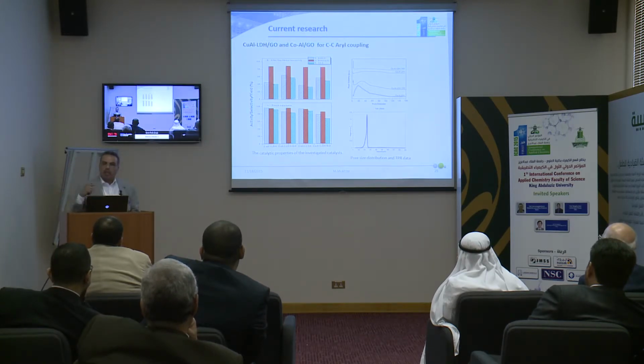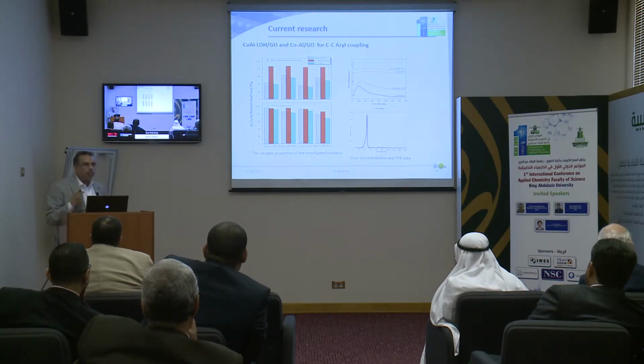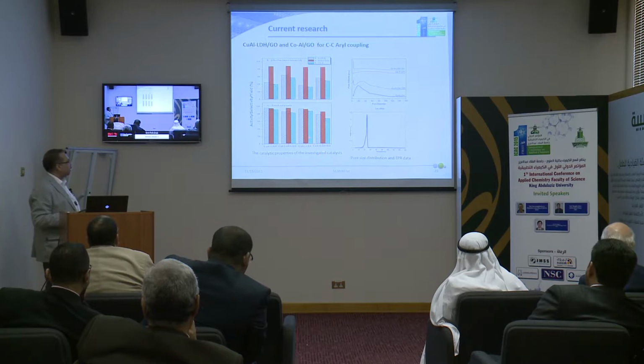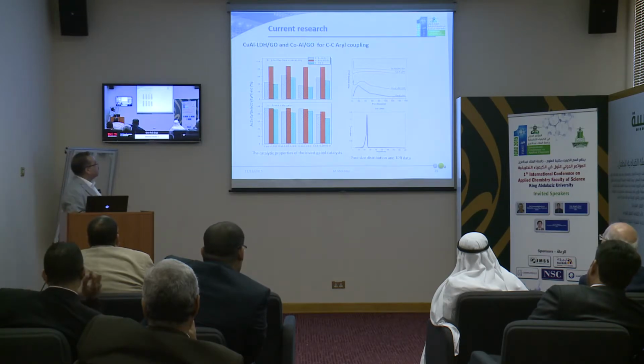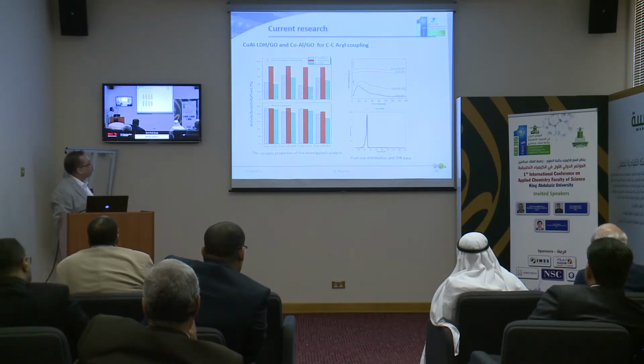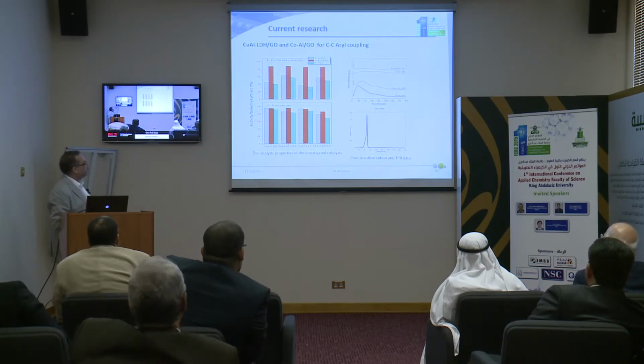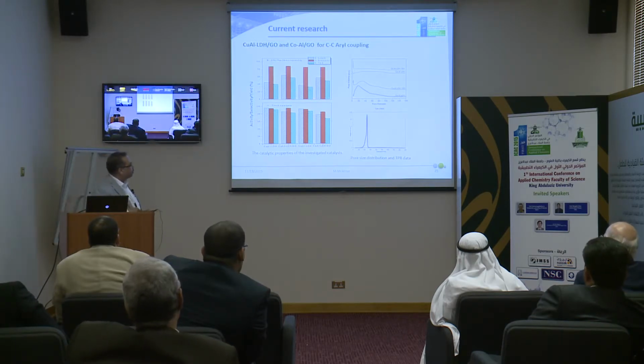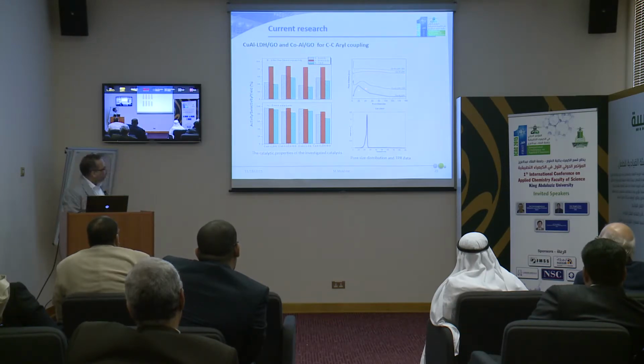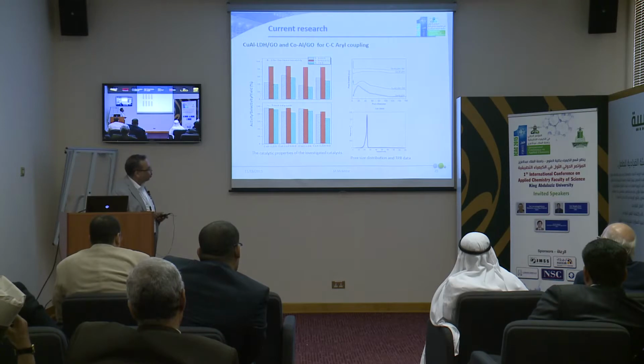So after filtration, dissolving, and so on, for the regeneration of the catalyst, you can find the graphene oxide supported catalyst gives better yield after 5 or 6 regenerations. And this originally comes from the unique properties introduced by graphene oxide as support for the layered double hydroxide, where first of all we have a change in the porosity of the material. This is the unsupported one, this is the supported one.